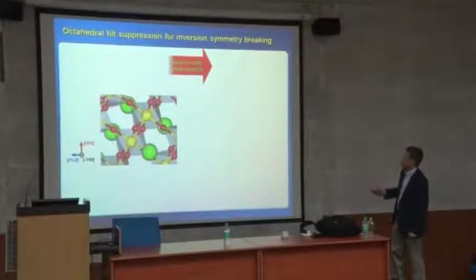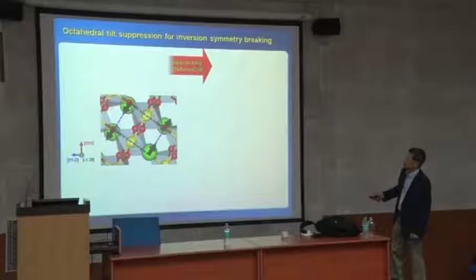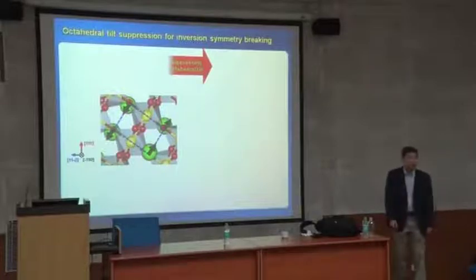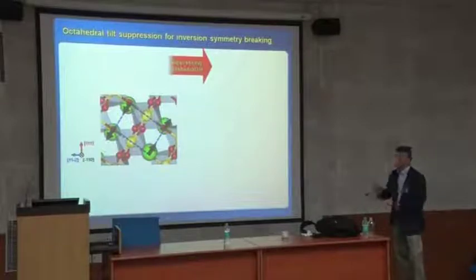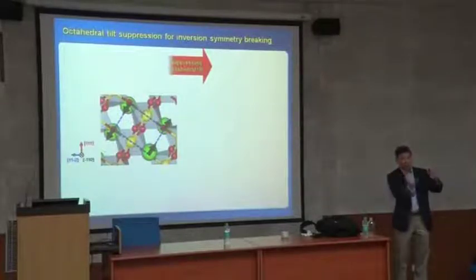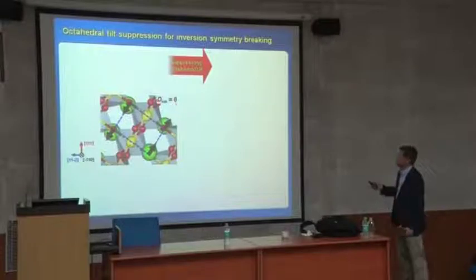And then suppression of this, you see that this structure here, direction of 111 direction here, and then this is a direction of 111. You see that this antipolar is exactly the same. This size and this size and this one and that one, exact same displacement, but the opposite. But somehow you change its octahedral rotation, it's a rotation pattern, and then suppressing this tilt. Okay? The octahedral tilt.